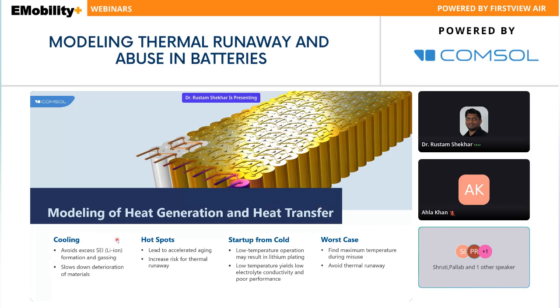So in some cases, when you are operating your battery at very high C rates, it will produce heat. So we want to cool down the battery to avoid excess heating, which will enhance the SEI formation and the gassing. So it will slow down the deterioration when we do the cooling. In some cases, the battery is working fine, the bed temperature is good, but still you will form some hotspots which will lead to the acceleration of aging and then increase the risk of thermal runaway.